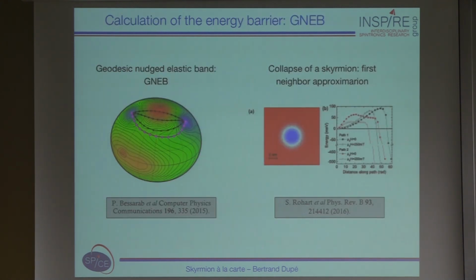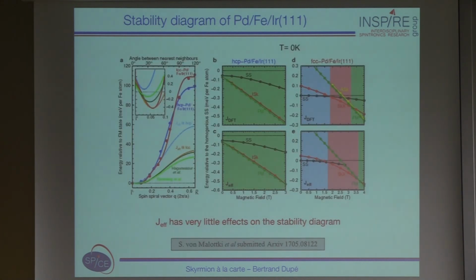So in order to look for the energy barrier, we actually need to do a nudged elastic band on the sphere. So it's geodesic nudged elastic band, it's GNEB. And this is actually the paper where it is proposed first, the paper of Pavel Bessarab. And there is one group in Paris, the group of Stanislas Rohart and the group of André Thiaville, who applied this method on actually cobalt platinum for the first time. And so let's apply it on palladium, iron, iridium.